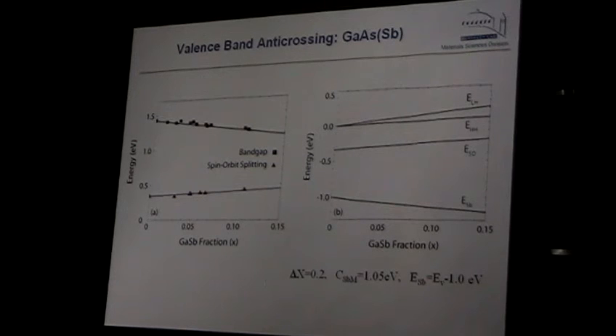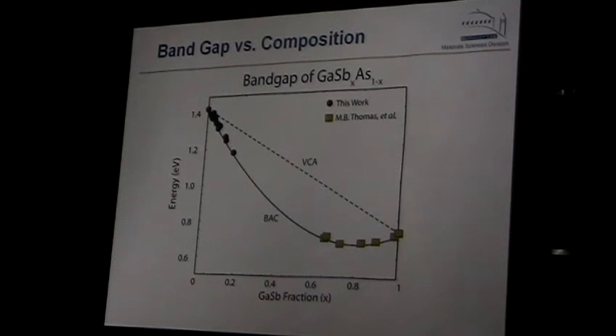Once you have this, you have all the band structure, and you can make a lot of predictions about properties. So this is how gallium arsenide antimonide looks, sorry. If you go from gallium arsenide, it goes rapidly down, and then, in fact, when you start with gallium antimonide, the gap is 0.7. It still goes down even if you add arsenic. Normally, you would expect it would go up. So this is this anti-crossing again, much less dramatic than in other cases.